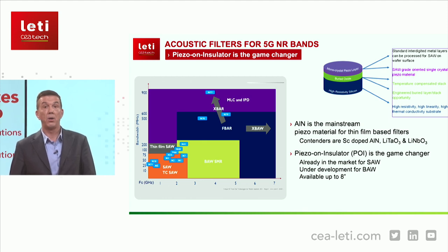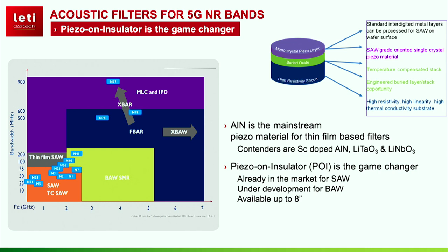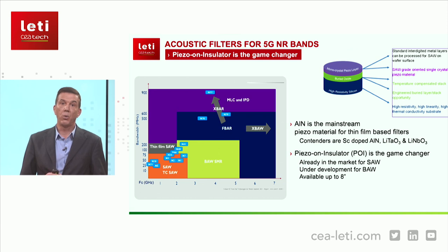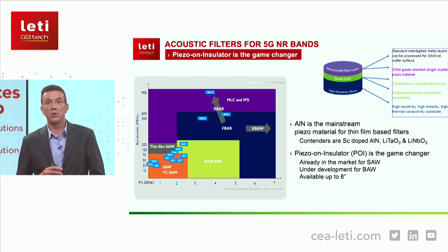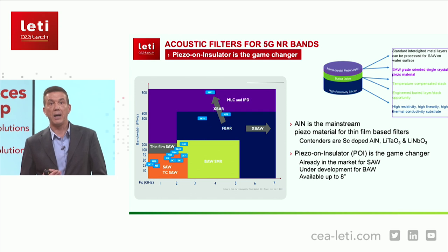POI stands for piezo on insulator. It consists of a substrate made of high resistivity silicon, a buried oxide layer, and on top of that, a thin layer of monocrystal piezo material, typically lithium tantalate or lithium niobate. The thickness and crystalline quality are very tightly controlled by the substrate manufacturer. The buried oxide helps achieve better acoustic properties, while the high resistivity silicon keeps the RF loss low.